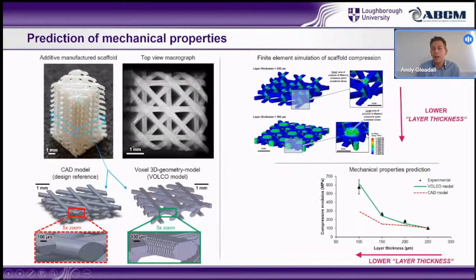Using that model in finite element analysis to get predictions of mechanical properties, I was predicting compressive modulus for these specimens, so we could do the experiments and then compare. On the right here, I'm showing the value of this approach, where the green line is the Volco model's geometry being used, and compared to the experimental data points, it's clearly matching the trend very well as we changed a parameter in this structure, which is layer thickness. As it goes smaller, the structure is getting more and more dense, which is what this image is showing. The top FEA image shows it when there's quite a lot of space between the layers, and the bottom one is when it's got very little space between the layers.